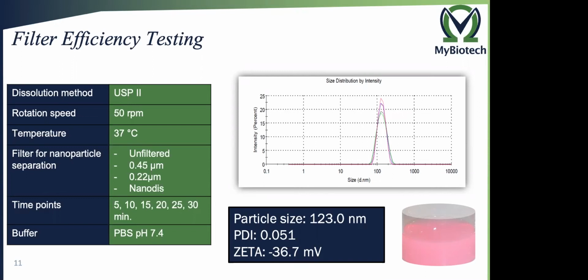And we had the zeta potential of minus 36.7 millivolt, which basically ensures the dispersibility of nanoparticles in the dissolution medium. Of course, another possibility of what can happen when you put your nanoparticles in the dissolution medium, if the nanoparticles are not stable enough, or if you choose the wrong dissolution medium, is that the nanoparticles directly agglomerate, which on one hand makes it easier to filter, but in such a case, since you change the particle size and the physical properties of the nanoparticles, you won't be able to come up with a result which would have an in vivo correlation or would tell you a lot about your formulation.